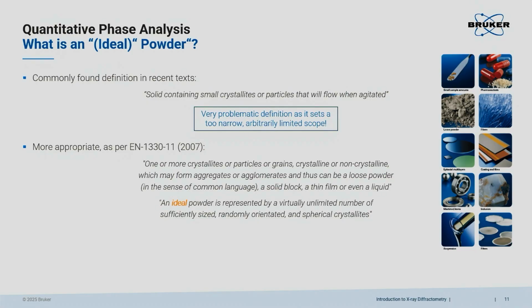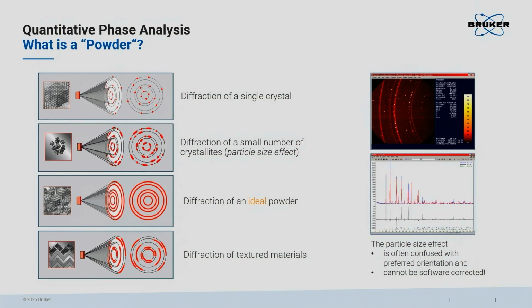An ideal powder, however, is what XRD needs. We need ideal powders, and they are represented by a virtually unlimited number of sufficiently sized, randomly oriented, and, that's the worst part of it, spherical crystallites. So in essence, we're never dealing with an ideal powder. We should, because the entire theory of powder diffraction is based on the assumption of an ideal powder. And we need to keep this in mind as soon as we deviate from this requirement. We introduce issues, like particle size problems, preferred orientation, you name it. And we have to think about what to do with it. They will always reduce our accuracy. It depends on the level of accuracy you need, but it is important to keep that in mind.